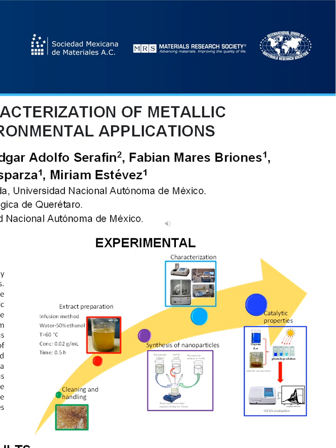The synthesis of the nanoparticles is carried out by mixing a precursor salt solution with the sargassum extract and sodium hydroxide to adjust the pH. The salts used were silver nitrate or chloroauric acid for the silver and gold nanoparticles respectively. The obtained nanoparticles were characterized by UV spectroscopy, FTIR, X-ray diffraction, and scanning electron microscopy. Finally, the catalytic properties of the nanoparticles were evaluated through the degradation of organic dyes, such as methylene blue, methyl orange, and methyl red.